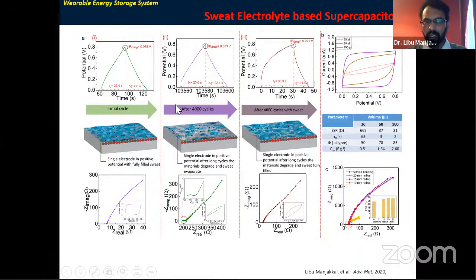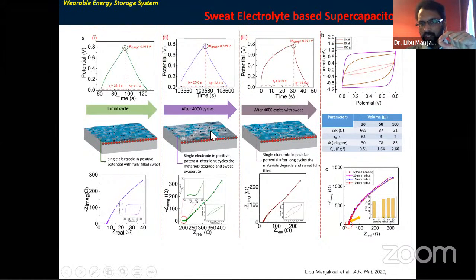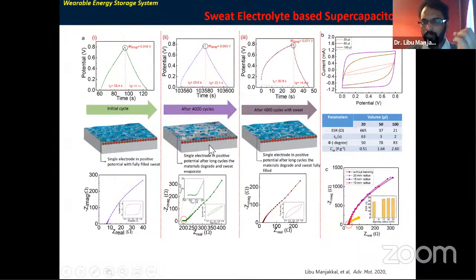Then I stopped the device and checked the surface of the electrode, and I noticed that initially a very good amount of sweat is distributed, but after a long measurement, the sweat is evaporated, and then it almost stopped working. It is not as good as initially. Then I again dropped the electrolyte on top of this device. Then I found that even though you drop again, there is enough sweat, but due to electrode property, the electrode property varied after 4000 cycles, and the performance also varied. You can see the PEDOT:PSS is easily dissolved in water. So the material property is very important to get high performance.